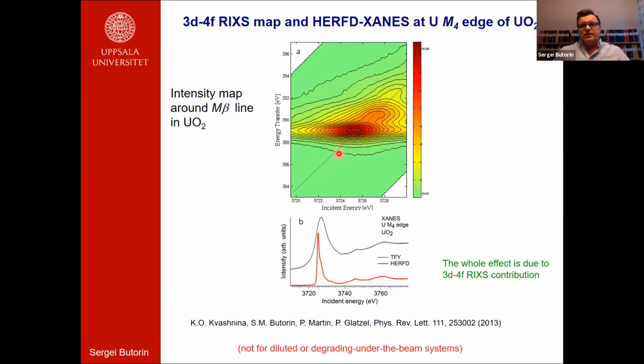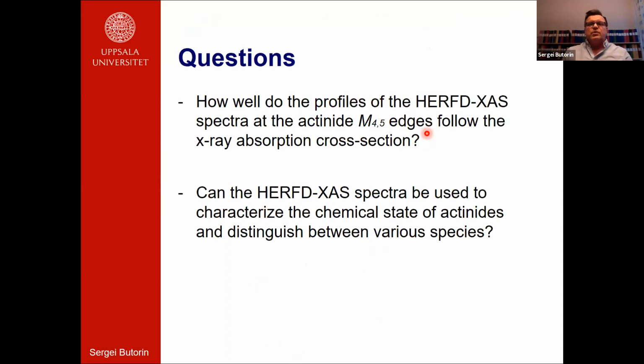Of course, this way of doing measurements is not always suitable, because it's time consuming. It's not possible to do it for dilute or fast-degrading under the beam systems. And also, if you make a cut, it's usually much noisier compared to a direct measurement of one HERFD scan. But using, for example, a Johann-type spectrometer can help with these problems. More and more researchers have now started to use this technique because of the improved resolution and enhanced sensitivity.